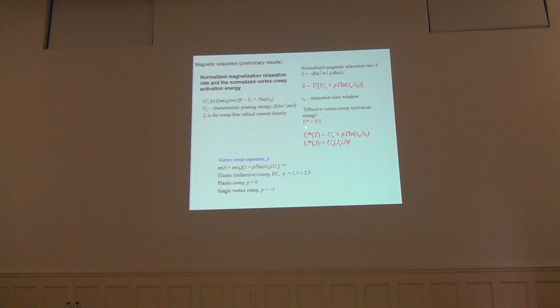And if we define the effective vortex creep activation energy as U star, which is temperature divided by the normalized relaxation rate, we have these dependencies. So the temperature dependence is a logarithmic one, with p the creep exponent, and the current dependence is again this one, with the creep exponent being positive for elastic creep and negative for plastic creep. So we have these values, plastic creep minus 1, and for single vortex creep, this one, it is in theory to be minus 1. So these are the preliminary results.